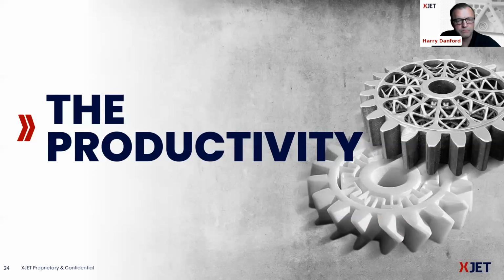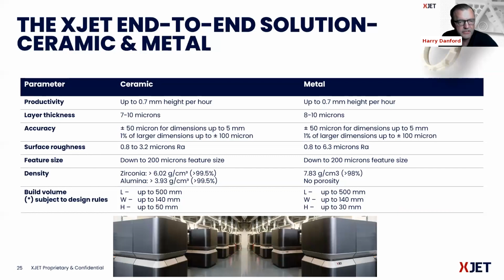Pushing over toward a discussion around the productivity of our parts. This is getting down into the meat of what the engineers always want to discuss and understand with our technology and with any technology, obviously. But we're basically building in the Z direction height around a little less than 1 millimeter per hour. Let's call it 0.7 millimeters per hour. Again, the layer thickness, 7, 8, 10 micron range. Part accuracy, we talked about, plus or minus 50 microns for dimensions up to 5 millimeters. If you've got something that's larger than 5 millimeters, you can calculate 1% of that larger dimension up to 100 microns. Surface roughness, we talked about 0.8 to 3.2 microns Ra for the ceramic and 0.8 to 6.3 for the metal.